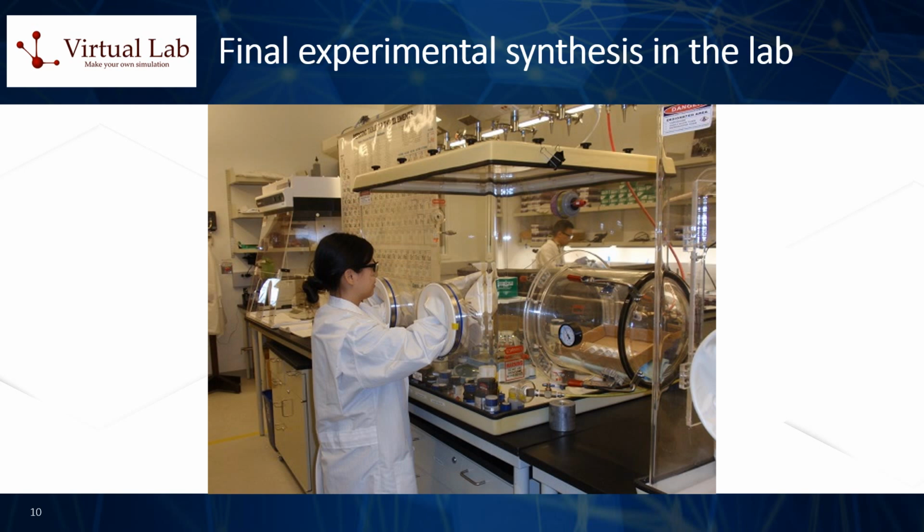In this particular example study, the authors were able to synthesize one of the most promising candidate binary alloy compositions identified previously during the computational screening, consisting in platinum combined with bismuth. As predicted from the DFT calculations, the experimentally verified catalytic activity of this new compound turned out to be superior to that of pure platinum.